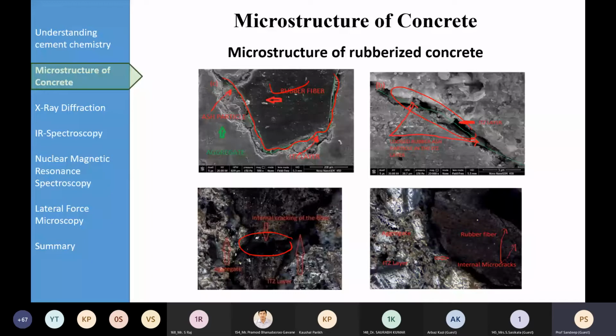So it will absorb the energy by cracking itself rather than the cracking of this cement matrix. In a sense, it will increase the impact resistance capacity of the concrete. And this is what you can observe also: if you use waste rubber fiber in the concrete and observe the impact resistance, you'll find a higher impact resistance. That is otherwise difficult to justify and difficult to predict by the conventional test. But based on that, you can correlate the effect of the microstructure on that.